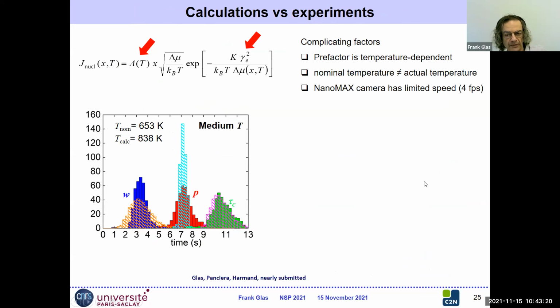Now, it's very difficult. I spent a long time trying to fit all experiments with the model that I developed. And very briefly, there are complicating factors. So I start from the nucleation rate, where basically we have two parameters, the prefactor and the edge energy of the nucleus. So these are a priori unknown.